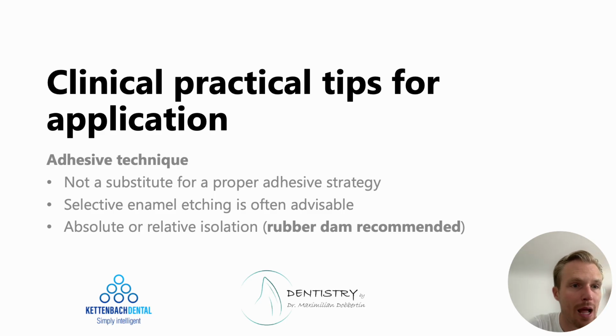As the clinical practical tips for application are a very strong key factor in the step-by-step protocol, the adhesive technique is something which is not to be underestimated. With the adhesive technique, we ensure a correct bonding and a maximum strength of the restoration towards the tooth, and it is not even a substitute for a proper adhesive strategy. More or less, selective enamel etching is often advisable, but even a total etching system can sometimes be even better in terms of cleaning the overall surface from the debris and the smear layer. The absolute and the relative isolation in this case is something which is very important to ensure that there is no kind of leakage.